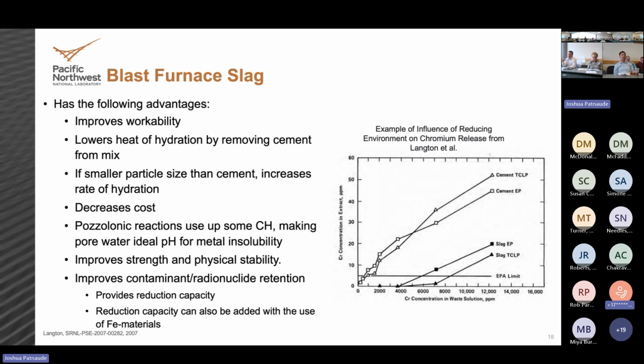Because the blast furnace slag comes in, it brings in reducing capacity primarily from its sulfur component. That sulfur component will go out to the contaminants that are redox sensitive, which chromium is. They can get involved in the redox reactions and reduce those contaminants from a mobile state to an immobile state. It has other benefits from a cementitious standpoint. It gives us some control over workability, how much heat is generated, porosity control. But the biggest piece in waste immobilization, if we're using slag, is it's in there to help with contaminant retention, both in short-term qualification testing and long-term performance.